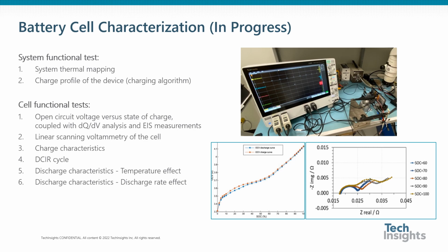In the functional cell test, we focus on the electrochemical response of the cells, including open circuit voltage versus different state of charge, and internal resistance measurement using electrochemical impedance spectroscopy at different state of charge, and DCIR methods. We also provide insight into the chemistry of the cell using differential capacity analysis, also known as dQ over dV map. We also investigate the effect of the temperature and discharge rate on the discharge capacity of the cell.